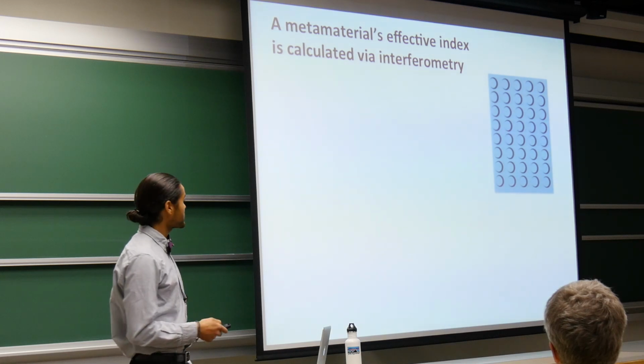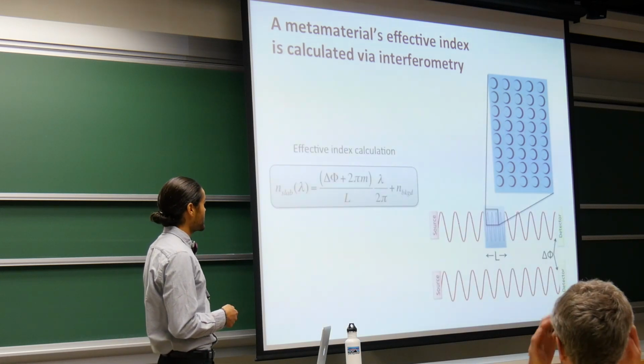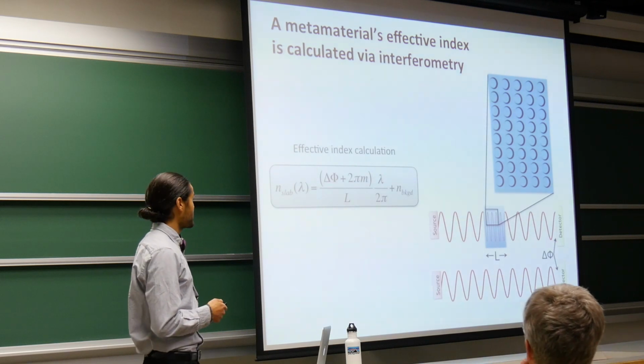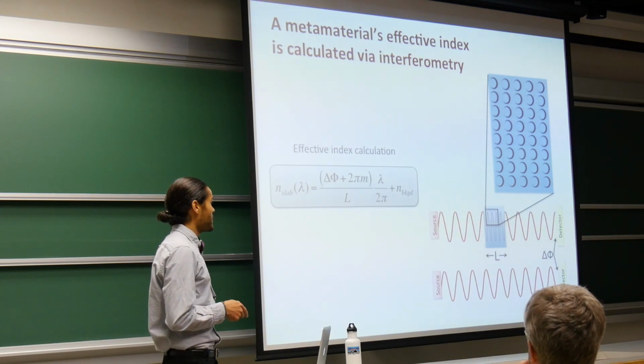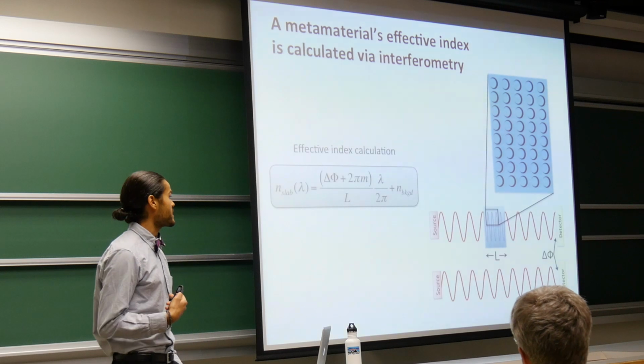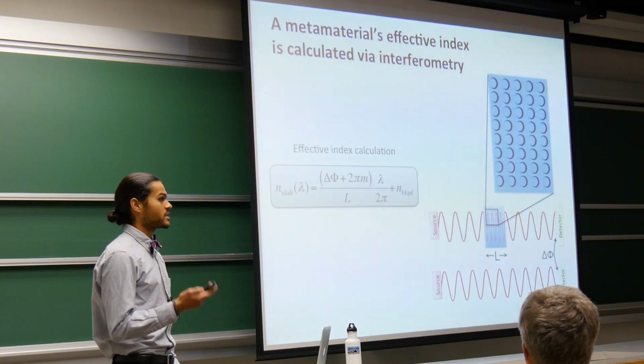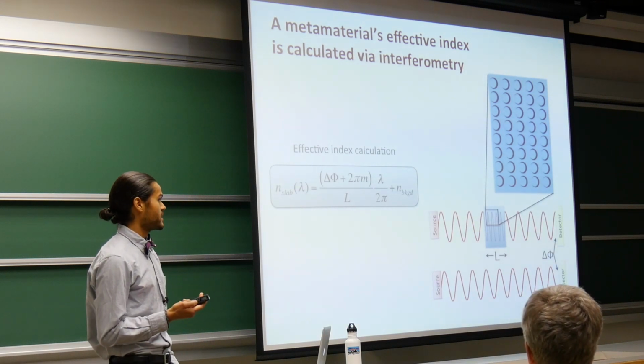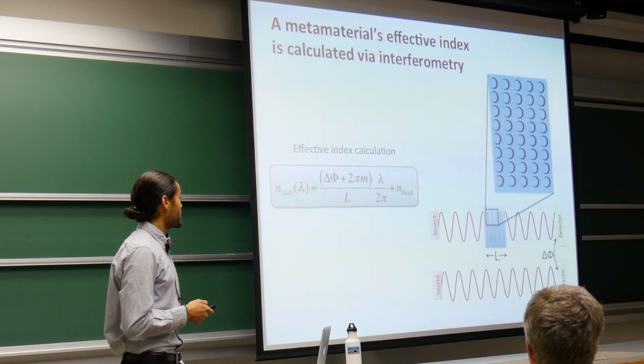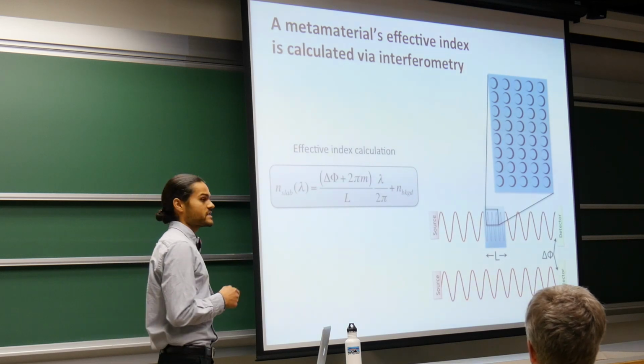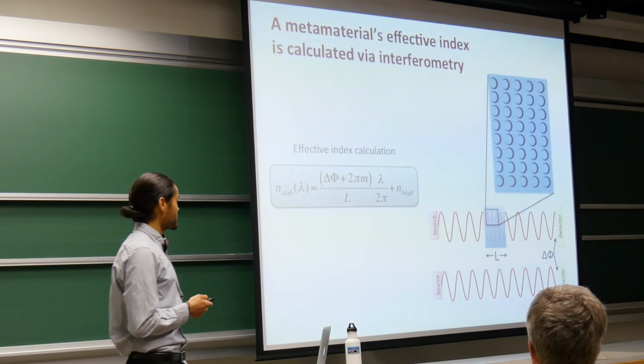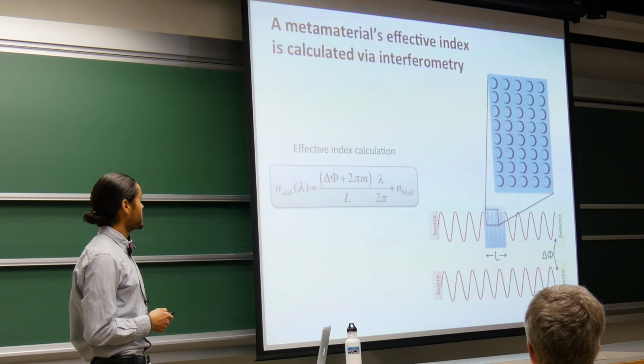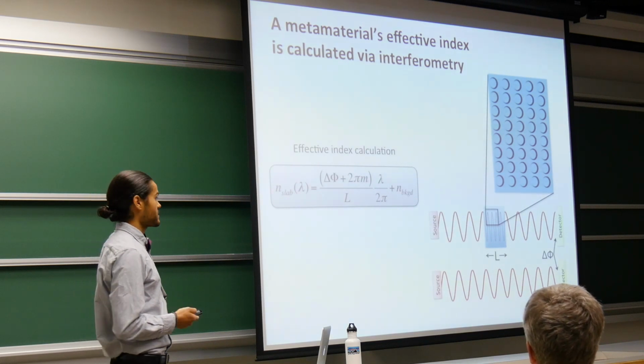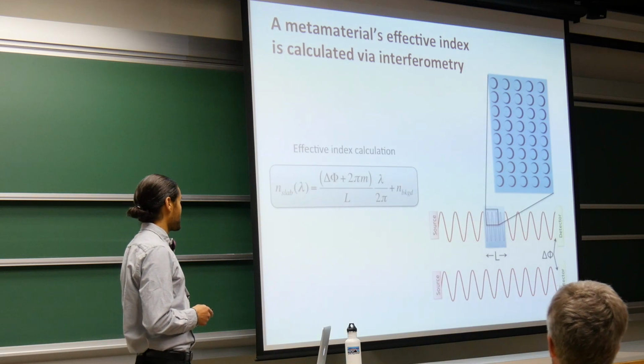To study their optical properties and measure their index, we use a numerical interferometry technique where we essentially measure the phase of light that has been transmitted through our metamaterial slab and compare that with the phase of light that has been transmitted through free space. Using the difference in these two phases and this relatively simple equation on the left, we can calculate the effective index for this metamaterial slab that we've created.